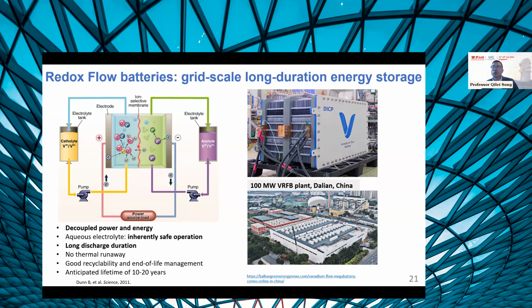This is a diagram showing the traditional vanadium flow battery. This flow battery is different from the lithium-ion battery. In the flow battery, you store the electrolyte in big tanks. You have the electrochemical reactions in the cell, but you separate the two chambers by an ion selective membrane. And then you can charge the battery with renewable energy, and you can discharge the battery, releasing it to the grid. The volume of the electrolyte can be scaled up, so you can change the energy you store in the system. You can also scale up the area of the stack, so you can scale up the power. This decoupling of energy and power makes the flow battery a really promising technology for larger scale energy storage.